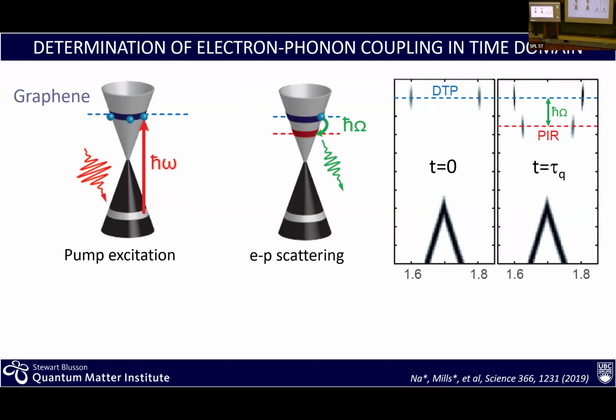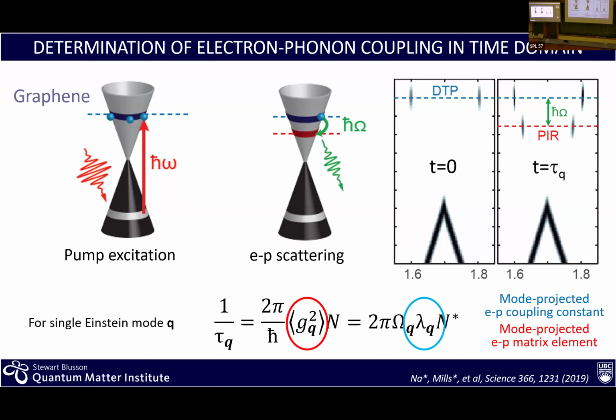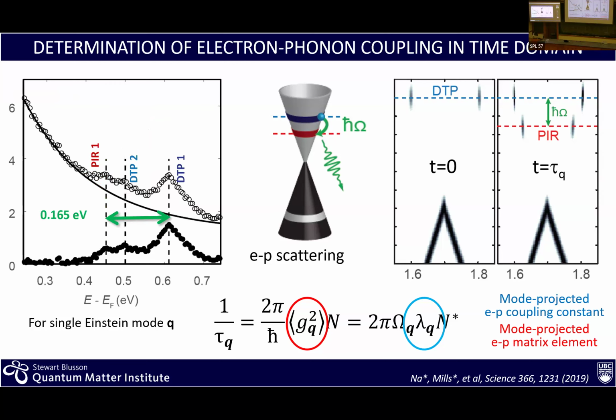And so if you now can measure this time by following the evolution of the intensity, you can use a very simple relation that connects the electron-phonon scattering time to the electron-phonon matrix element or the electron-phonon coupling directly, where lambda is the coupling between electrons and phonons, n is the electronic density, omega is the frequency of the phonon. So this is one case where you can use a very advanced technique to extract a very microscopic parameter, lambda or g, the matrix element, directly just by watching how the intensity is evolving in the experiment. Now, I don't want to delay this, but tomorrow we'll discuss this in great detail.